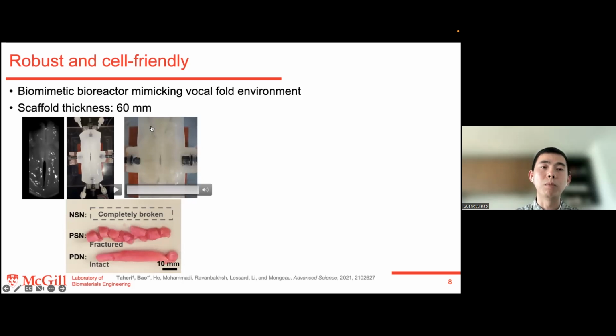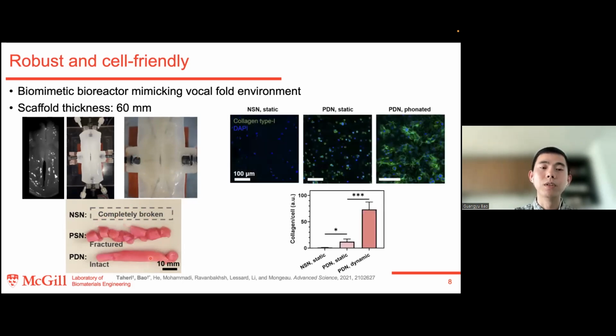And at the same time, we applied 6 million cycles of mechanical stimulation while doing the cell culture. After the cell culture, we can see that the standard hydrogels are either completely broken or broken into pieces. But our hydrogel maintained the whole piece, especially in the center where the stress is most concentrated. And in terms of the biological performance, the cells could not secrete much collagen within the nanoporous hydrogel, which is commonly used in the field. But in our porous hydrogel, even without the mechanical stimulation, it already promoted collagen synthesis by the cells, which is indicated by the green color.